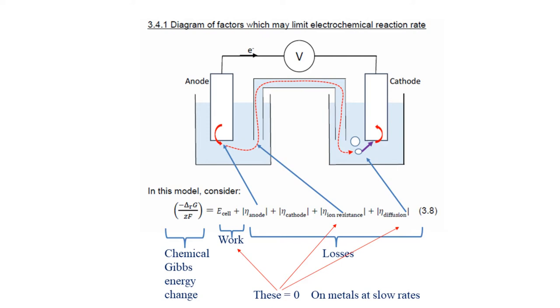We have metal dissolving from an anode, we have some ion transport in solution, we have a cathode reaction, so that might be something like a hydrogen discharge with hydrogen gas being evolved, and we have electron transport between the anode site and the cathode site. Several steps happen at the same time in this corrosion process. And in a full equation describing the speed of corrosion, I might need to consider any one of those being rate limiting. To start with, to make a simple equation describing corrosion speed, I want to only consider one per electrode thing being rate limiting.